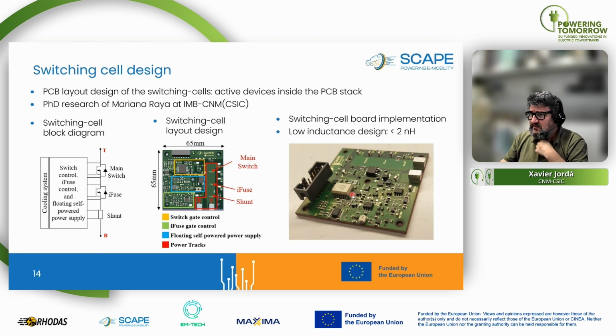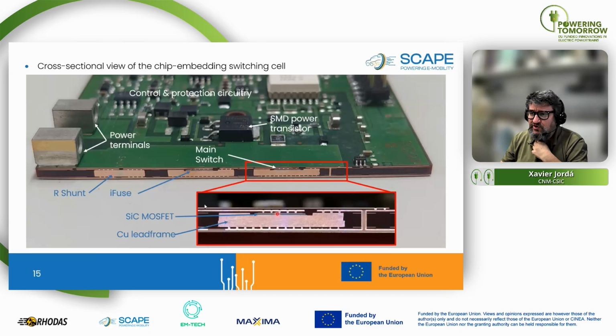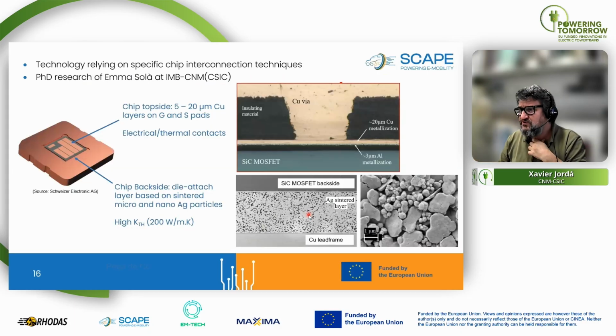Well, then this is the switching cell that we have developed. You can see here a cross-sectional view of this development. You can see here the shunt, the iFuse, the main switch. Okay, you can see here in gray, this is the silicon carbide power MOSFET. And as I also mentioned before, for achieving these results, it's very critical to have relatively thick, this means between 5 and 20 microns copper metallization on the top side pads of the power devices, on the silicon carbide MOSFETs.